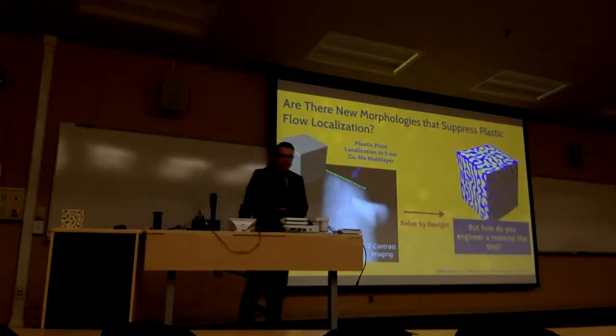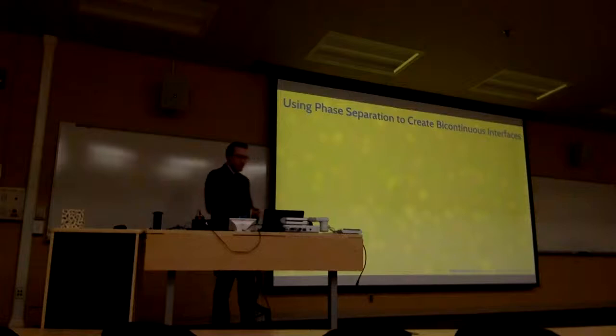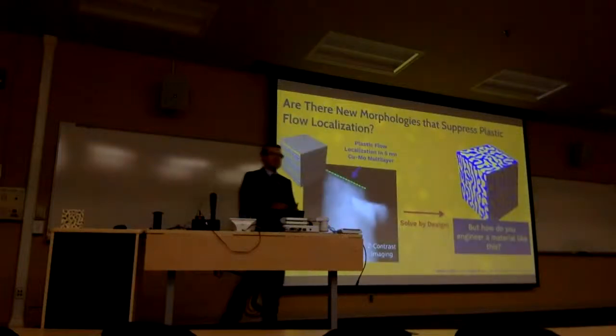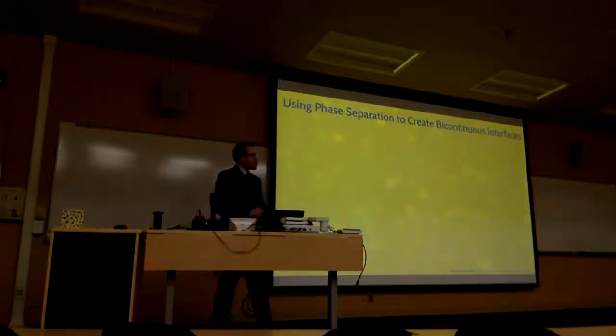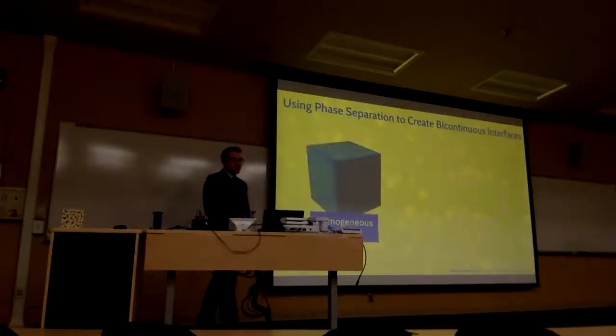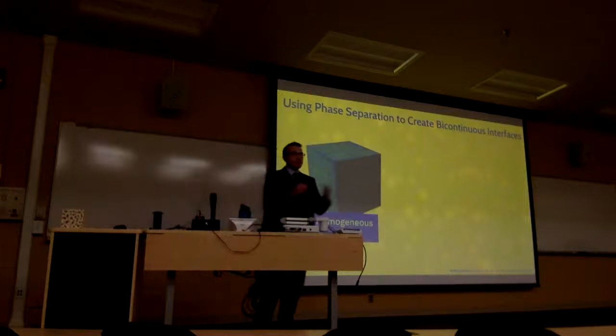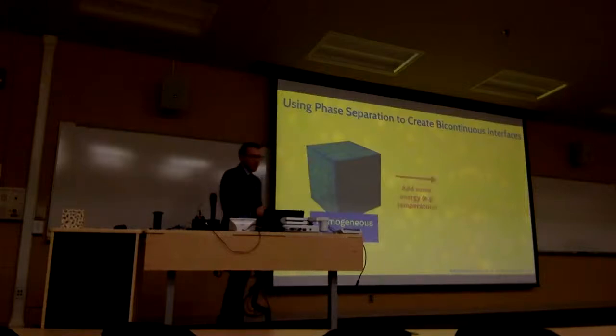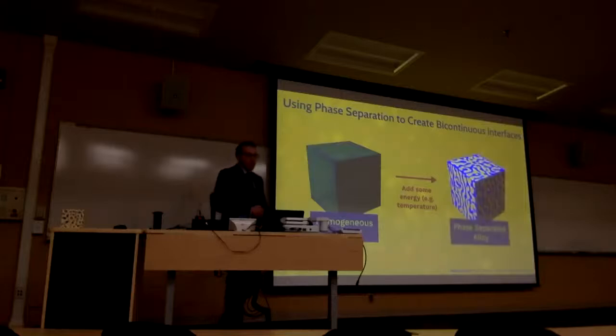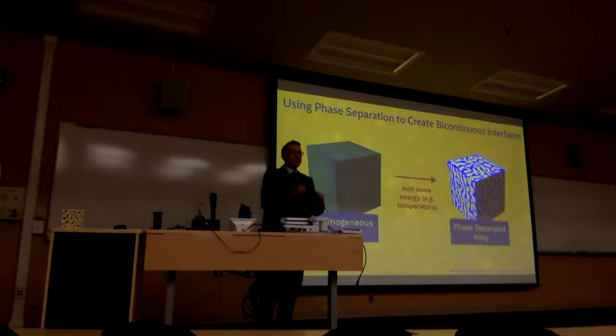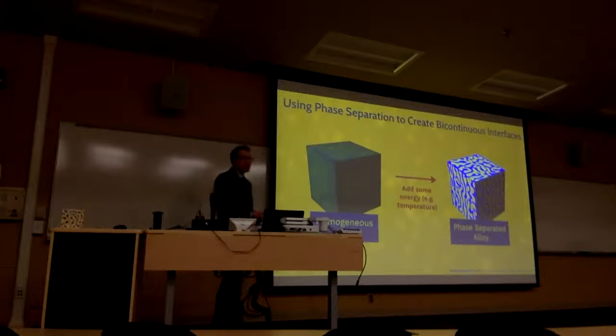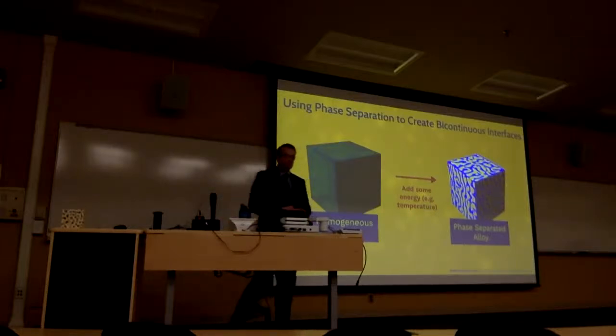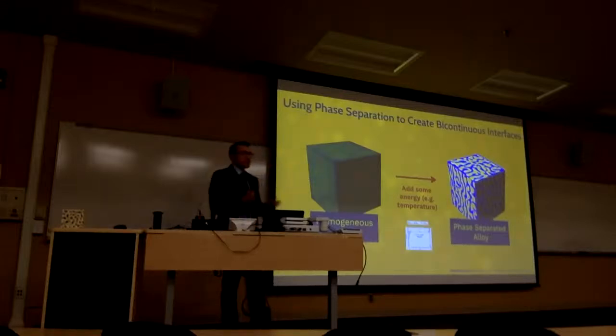And so the question that we ask then is, how do you engineer a material that looks like this? Well, in fact, this structure looks like, to some of us in the room, a phase-separated alloy, a phase-separated structure. And to a material scientist, phase separation looks something like this. We take a homogeneous alloy of a certain material combination, we give it some energy, for example, temperature, and we can phase separate that alloy into 2 distinct domains, in this structure, the yellow and blue domains. We can actually design very sharp interfaces between those phase boundaries. Now, I said this occurs for very specific combinations of materials.